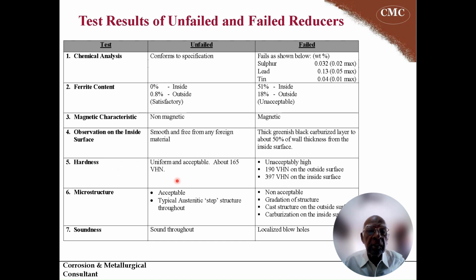So here is the hardness variation. You can see about 165 VHN, and it is uniform and acceptable. Whereas here the hardness is unacceptably high as compared to 165. Here we are seeing a gradation of 190 to 397. Both are very much higher than this value. Hence, since the hardness range is unacceptably high, brittle fracture can easily take place due to some temperature or load variation. So the summary: the microstructure is acceptable for the unfailed one, and it is a typical austenitic, so-called stepped microstructure, whereas it is a non-acceptable microstructure in the failed ones.